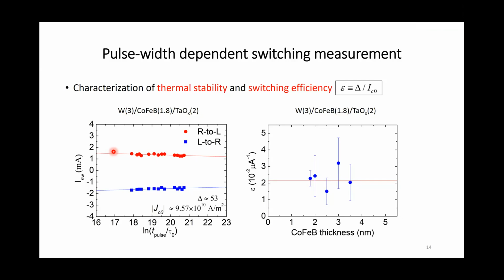So even now we're not so sure. For instance, the thermal stability can be calculated using the anisotropy energy constant times the volume, but we're not sure what KU we're referring to. Maybe it's the magnetocrystalline anisotropy, or locally there is some shape anisotropy, but from the AMR measurement, we don't see any shape anisotropy at all, at least in those samples prepared by ourselves.